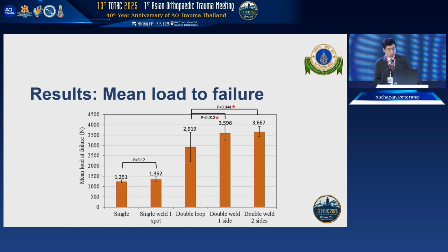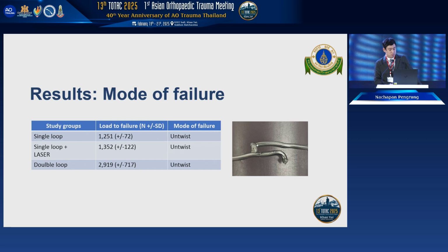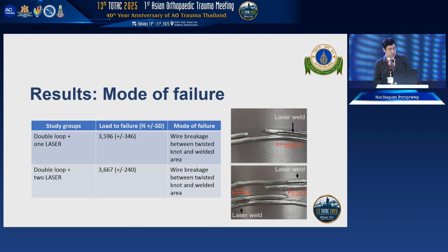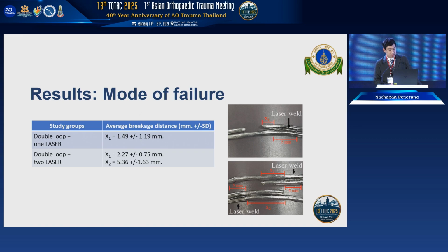And this is our result. It's confirmed that the double loop wiring provides significantly better biomechanics than the single loop, as all of you know. If you focus only on the double loop groups, either one side or 2 sides of weld provide significantly better biomechanics than the conventional double loop group. But there is no significant difference between laser and without laser in the single loop. For the mode of failure, the single loop with laser and the conventional double loop failed by untwisting of the tightened wire. The last 2 groups, with 1 laser or 2 lasers, broke at the wire between the laser and the twist.